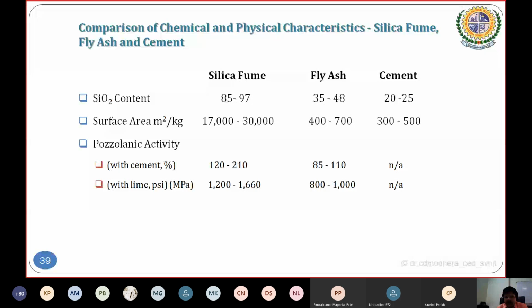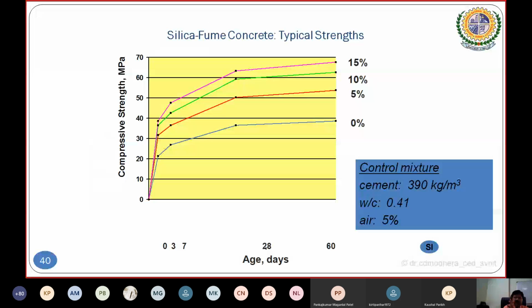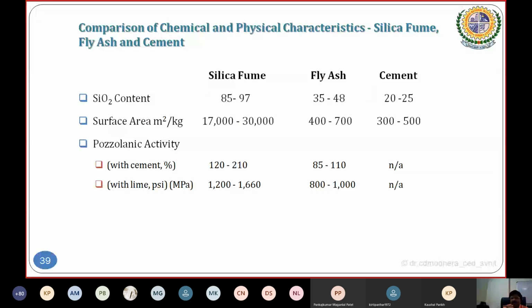This is basically, if we are talking about only three parameters, then as far as SiO2 content is concerned, silica fume will have 85 to 97 percent. If we compare with cement, cement has 25, and fly ash has 35 to 48. Surface area, remember I told you 3 to 5, I have taken in centimeter square per gram 3250. In meter square per gram it comes to 325 or 300 to 500. That is the range available for cement.